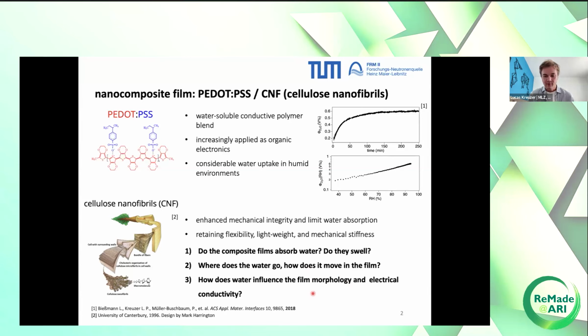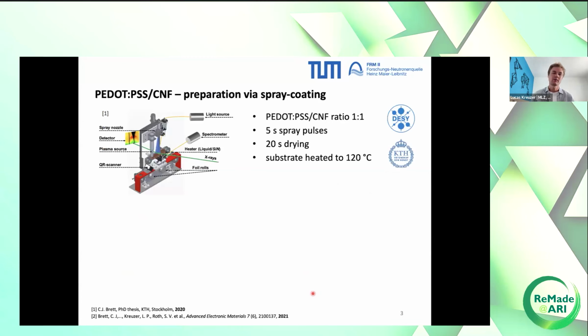Now, before we can tackle these questions, we need to prepare our films. And this we can do with a technique called spray coating. A former PhD student at KTH, his name is Calvin, developed this spray coating setup where you simply mix PEDOT:PSS and CNF together with a ratio of 1:1 in an aqueous solution, so everything is water-based. That's quite nice. And then you have a certain spray coating protocol.